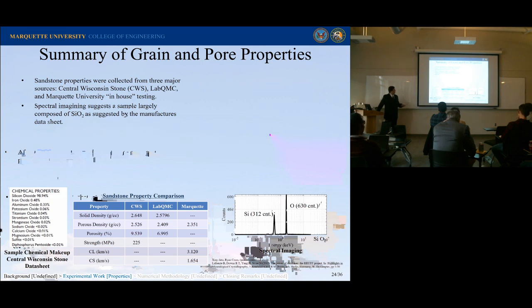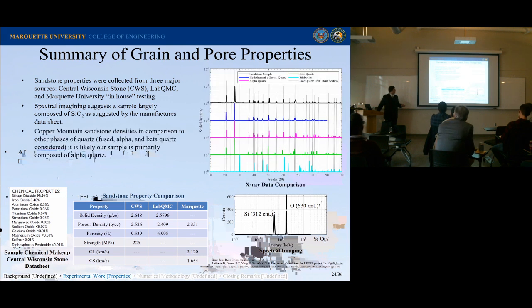Spectral imaging: I was able to put this into our spectral imager. As you can see, it's mostly SiO2, which is a good sign. And then I put it into an X-ray data comparator, and I was able to see that the grains we mostly had were probably alpha quartz. You can see we've got a lot of peaks that match up really well. So with these, I can build models later on.